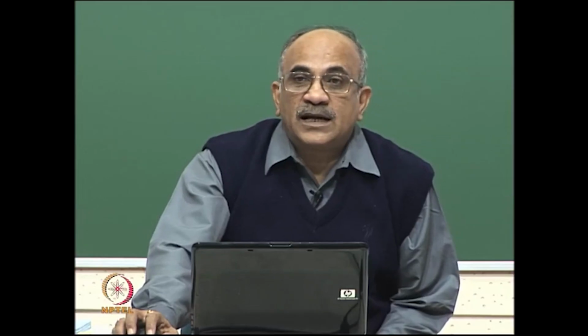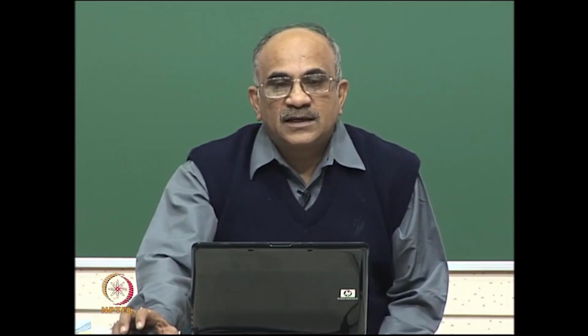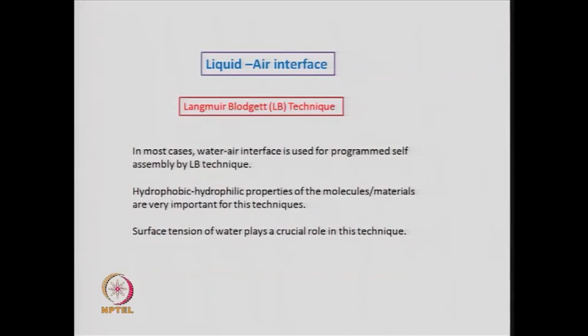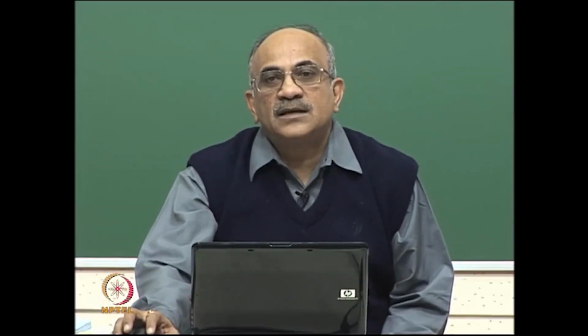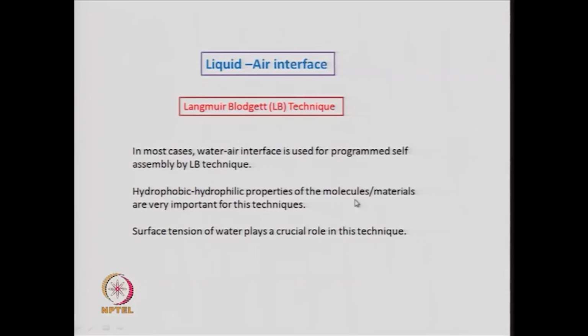So, you are basically looking at the water air interface, and there the hydrophobic and hydrophilic properties of the molecules are very important for this kind of technique. For example, you have water, so you will have hydrophilic interactions. You can have a silica surface which is hydrophilic, and you can change the hydrophilic silica surface by using a silane, say an alkyl silane, and make it hydrophobic.